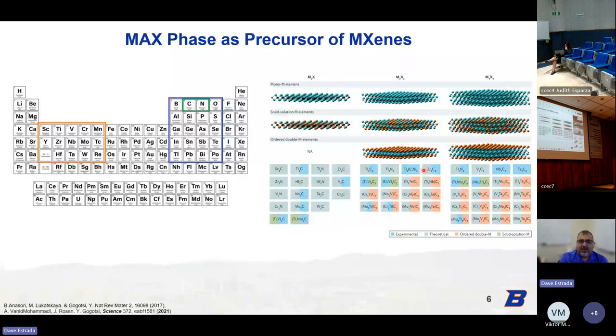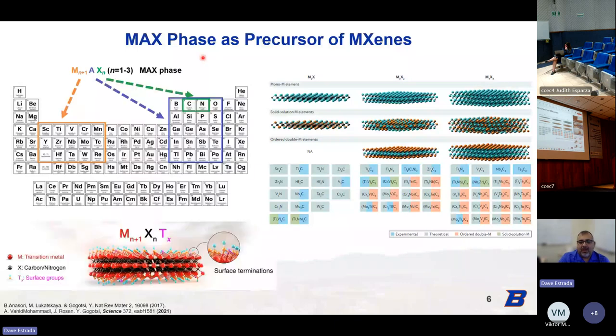For this, we move away from bismuth telluride and we go to a new class of materials known as MXenes. If you're not familiar with MXenes, these are etched out of MAX phase ceramics, where M is an early transition metal, A could be any of these elements shown here in the blue box, largely aluminum, silicon, and germanium, what's been reported in literature, and then X is carbon or nitrogen. These MAX phases can have different stoichiometries of M, n plus one, A is typically just one, and then X to the n, right?